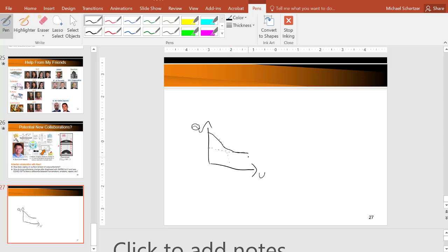There are a lot of different explanations for why this happens. Some people have seen that in some cases you're pulling on the droplet so much that you actually eject small droplets from the surface. There are other questions about the force vector always going perpendicular to the surface, so as it gets flatter, you're losing force. This is an open fundamental question, but it definitely happens. Since the last time you presented that, no one's really answered. I have not seen a definitive answer.